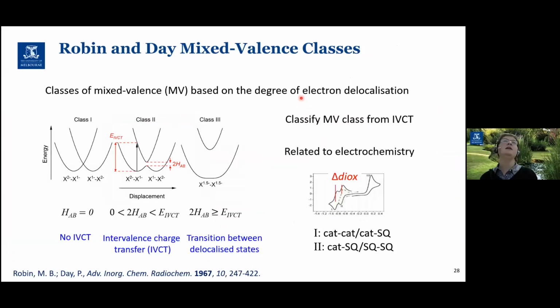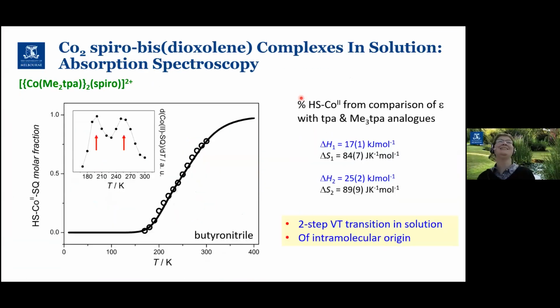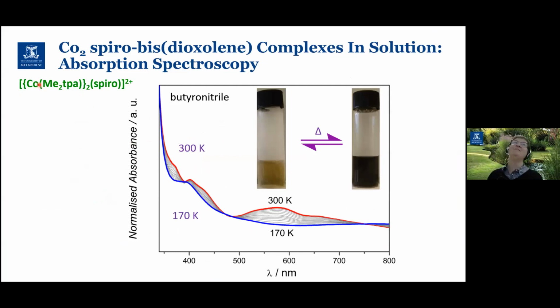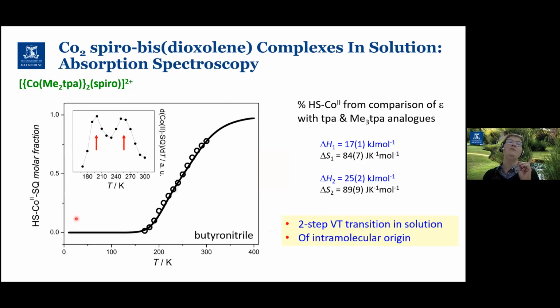Yes, it is. I actually have some extra slides. So, with that dimethyl TPA spiro, it does do the transition, this is in butyronitrile. It goes yellow to blue-green, with isosbestic points, it's quite beautiful. If we plot from that data the fraction of high spin cobalt-2 semiquinone versus the temperature, it's a distorted sigmoidal profile. And if we take the first derivative of that, we do see two distinct peaks.